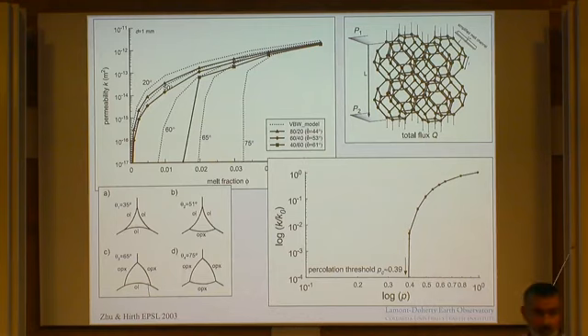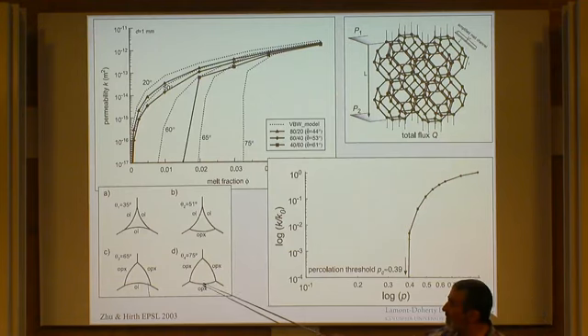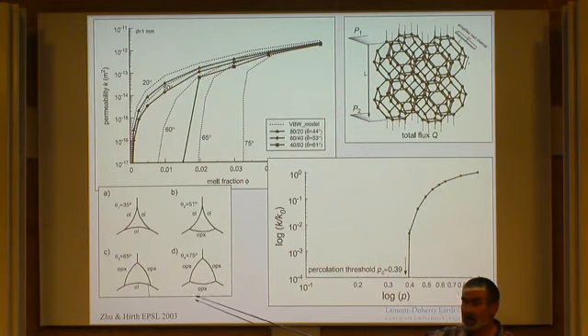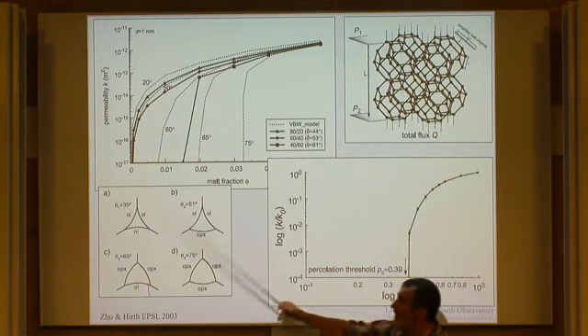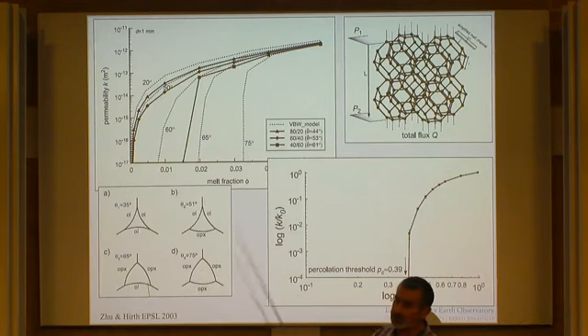But the von Bargen and Waff model assumed homogeneity, right? It just assumed wetted grain faces. This goes back a ways. Toramaru and Fujii wrote the first paper on this, as far as I know, in 1986, and it's been an experimental observation. A lot of times when you do experiments on partial melting of mixed phase peridotites, the pyroxene grain boundaries aren't wetted. So there's a lot of empirical support behind this kind of approach.